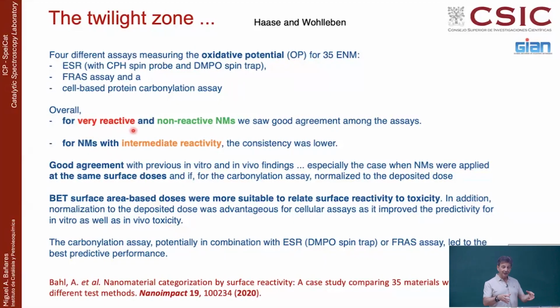They know that for the very reactive nanomaterials, when you make a cell culture for 24 hours, at the end of the day, most of the cells die. For non-reactive materials, after 24 hours in this cell culture, all the cells are alive. But the problem is that materials that have a moderate oxidation capacity basically didn't kill the cells. And that was puzzling because, okay, if it has an oxidative capacity, it will ultimately kill the cell. But it didn't kill them.